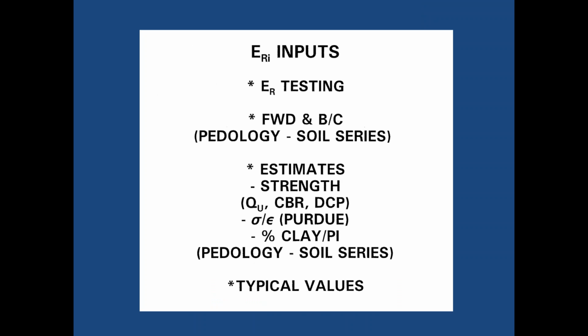How do we get these modulus values? That ERI value is the modulus at a repeated deviator of about 6 psi. We can actually do the testing. We have found that we can develop that from falling weight deflectometer and back calculation procedures. And from that, tying into pedology and soil series, you can say, hey, if you've got this particular soil series, you're probably going to have these kind of moduli values with the various layers. Or we can estimate it based on strength, unconfined strength, CBR, dynamic cone penetrometer.